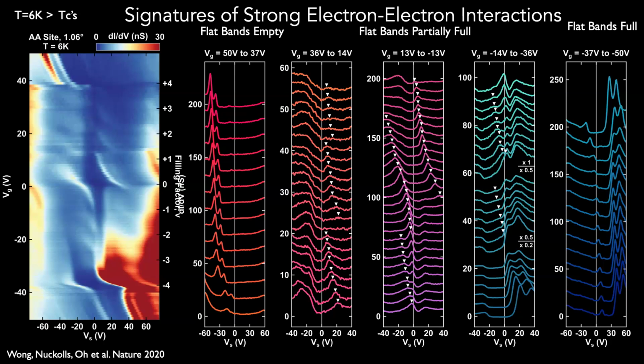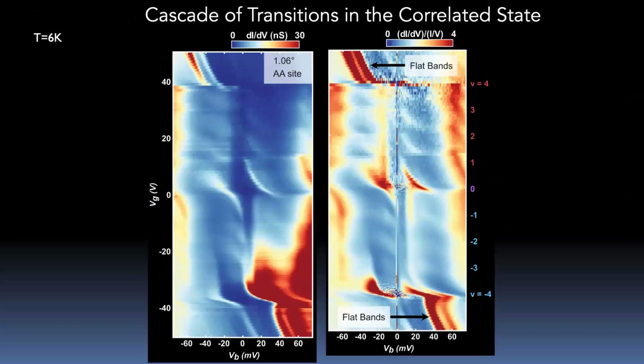So let's look at the data here. These three lines here: this is just all this information plotted in a color plot. These two lines are the two flat bands coming in. These features are these broad features, and then this is where the flat bands exit. A way to bring out the features is to take the dI/dV and divide it by I/V. This is because when you do experiments at every gate voltage, the tip heights may be slightly different because the density of states is slightly different. That takes it out of the normalized quantity. So what you discover is that there is a cascade of features in this data, much sharper here and then over here, at every quarter filling. And this is an experiment that's done at very high temperature. So this, if you want to think about it, is the normal state of this twisted bilayer graphene.